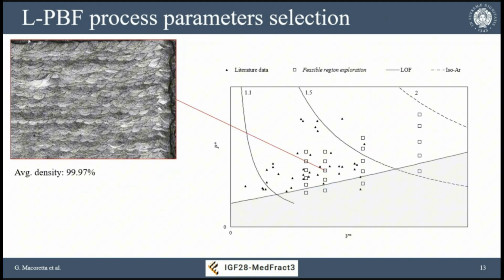If we are in a region above the lack of fusion boundary but at power that is not extremely high, we can produce very dense material with an average density of 99.97%, with very regular melt pool tracks, as seen in the image where the material is etched with color etchant showing traces of precipitation on melt pool boundaries. This shows the process is most stable.